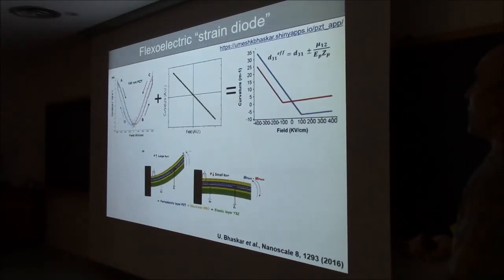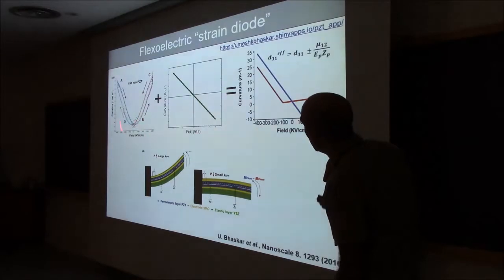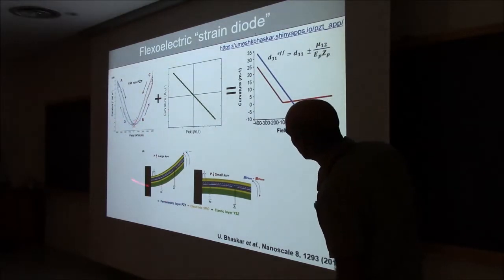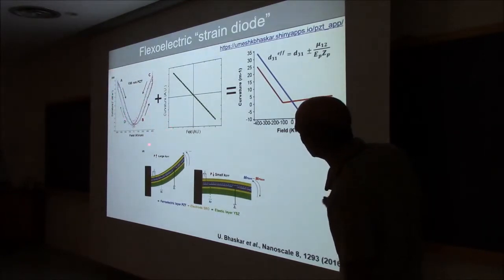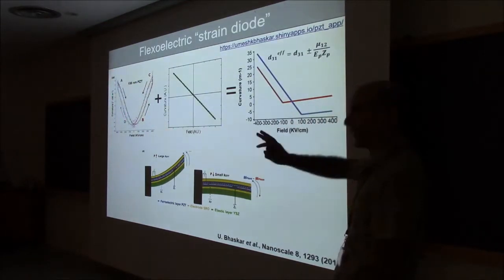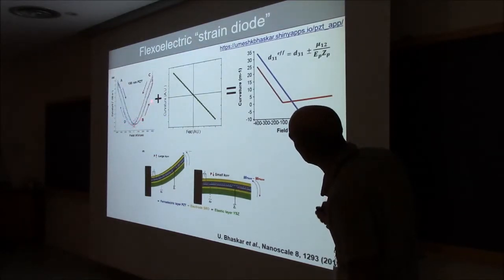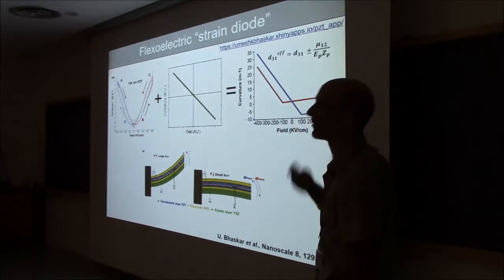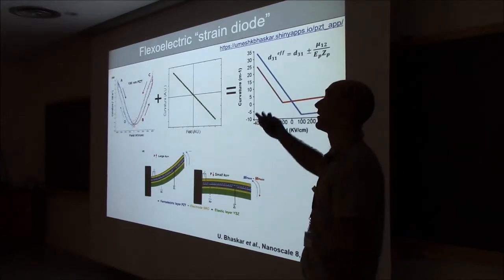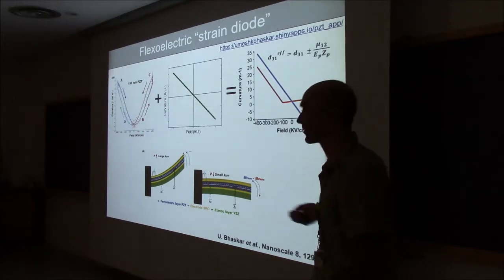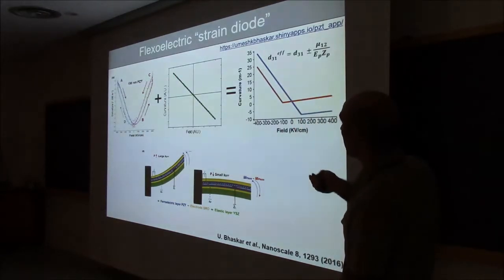Okay, so one thing that you can do, for example, is if you have our bimorph actuator, remember the bimorph piezoelectric actuator, and you look at the bending as a function of voltage, assuming that this is perfectly ferroelectric and there's only a ferroelectric contribution, so basically you see that the bending is proportional to the polarization. If you switch the polarization, you also get the same amount of bending. You get what's called a butterfly loop. If you look at the strain versus voltage response on a ferroelectric, this is what you get. Okay, butterfly loop, symmetric.